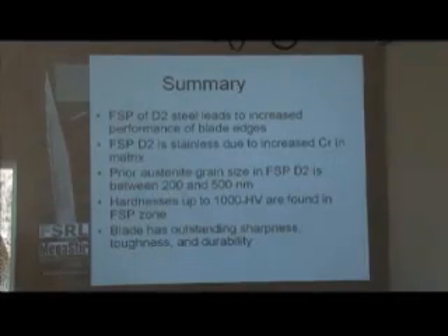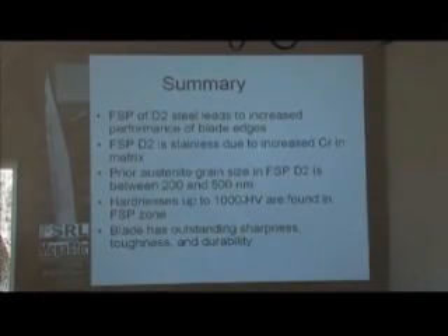The grain size is between 200 and 500 nanometers, 1/10 of the grain size in traditionally processed steels. We're off the chart on grain size, and down below. We're off the chart on hardness. We have hardnesses up to 1,000 Vickers, and we have outstanding sharpness, toughness, and durability in the edge as a result of this new material that's created in the friction stir processed region of the blade.